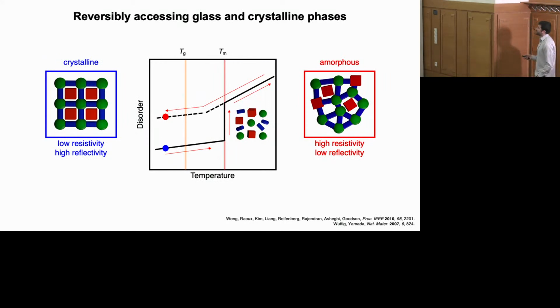In a phase change memory, one can think about storing information, so bits, in crystalline versus amorphous states of a material, as long as you have a difference in some type of optical or electronic property. So you imagine this is your 1 and this is your 0 in a storage system. And you can induce these transitions basically by taking your crystalline material, heating it up to form a liquid, rapidly quenching it to form the glass, and then annealing it back into the crystalline phase.